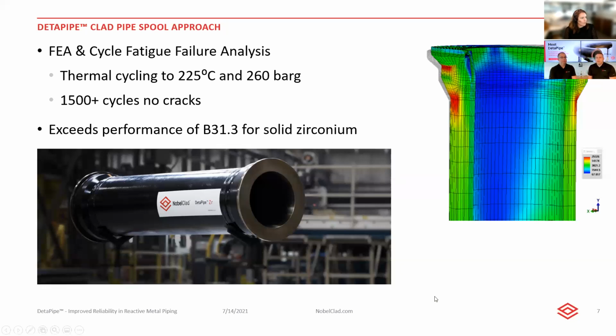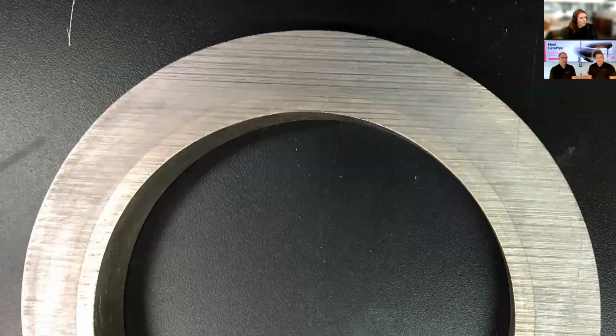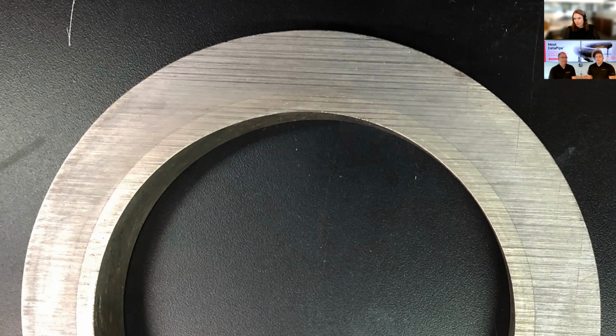So recognizing that, probably one of the biggest bangs for the buck, in the next slide, folks may say, we're used to you guys offering very reliable clad plate. Well, one of the things we did is we cut the pipe apart destructively, and we wanted to ensure that there was good gripping force between the pressure boundary wall and the cladding layer. And so we did that. This was actually a sample of, you can see on the OD, the carbon steel, and on the ID, the zirconium liner. And we actually did some push-out tests with that. And even at high temperatures, we have good locking force of the cladding to the pressure boundary.